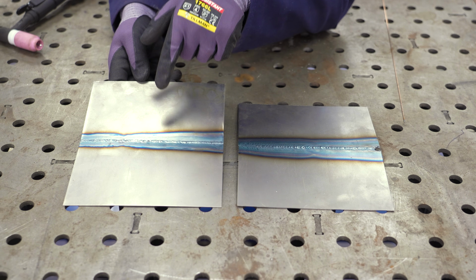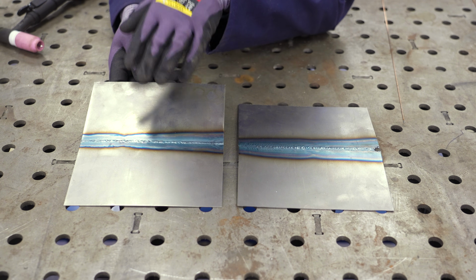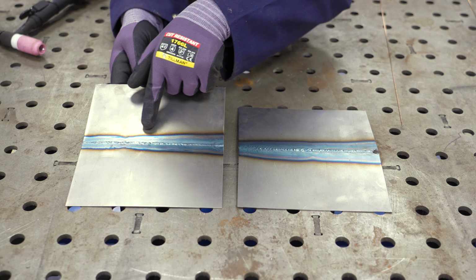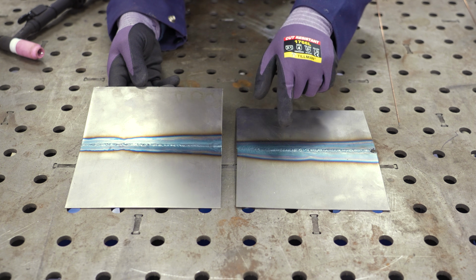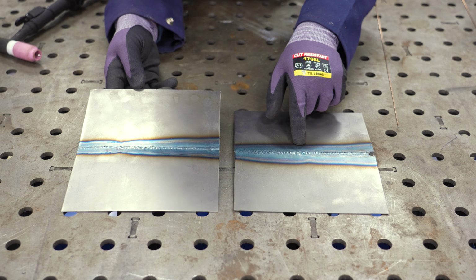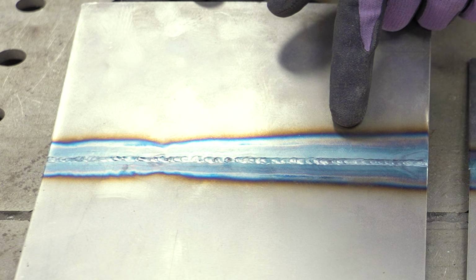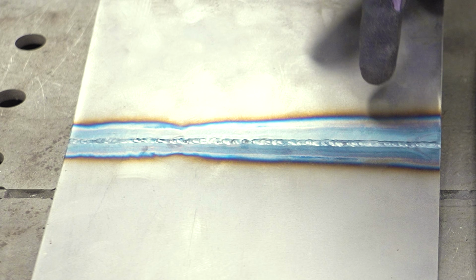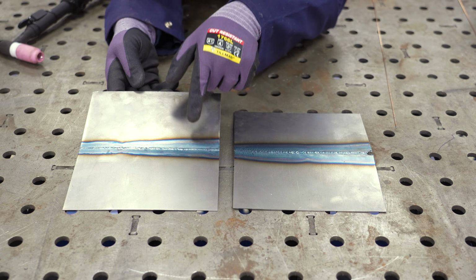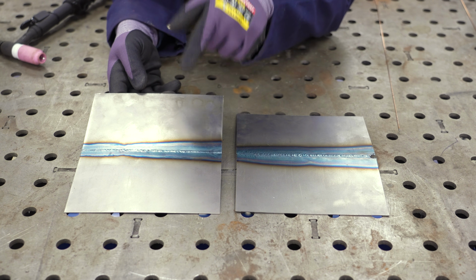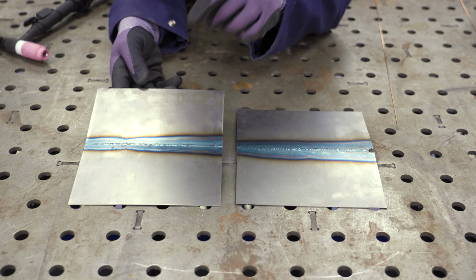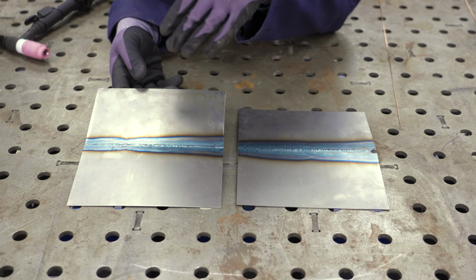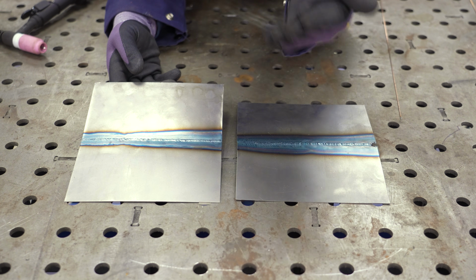This is the panel I did the high frequency pulse with, and you'll notice that the heat affected zone, which is this blue haze, is much smaller than it is with the low pulse. Also, you'll notice that my heat affected zone got a little bit wider towards the end because I slowed down. That was mainly because I was realizing that my penetration probably wasn't as good as I wanted it to be, and also because this panel was getting heat soaked. And as it got heat soaked, the temperature began to rise in the panel, and that's the result right there.